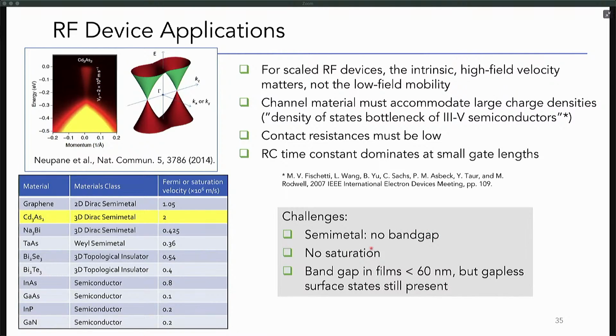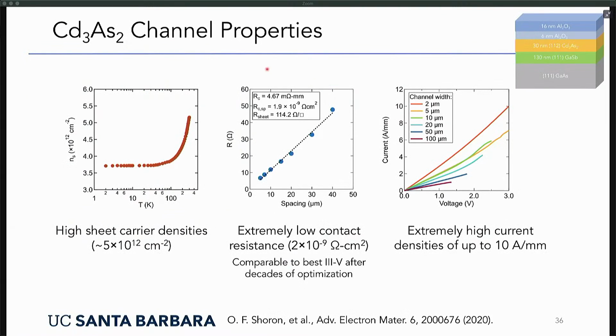And this also means that there's no current saturation. And as I just showed you, even if you open up a band gap in the bulk, you still have these gapless surface states. So that's one of the challenges with making electronic devices with these materials. But let's look a little bit at the basic channel properties, as a channel material for transistors, and it turns out they're very, very good.